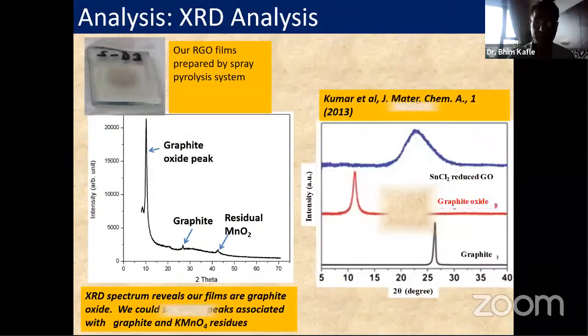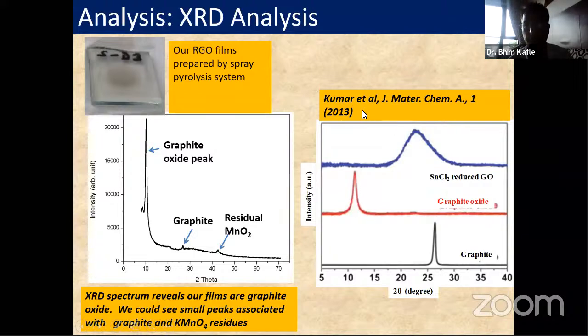And then here I would compare the XRD of the sample. This is the XRD spectra of our sample. You can see this is the graphite peak here, and this is the graphite peak published by Kumar et al. in 2013. You can see the appearance of this peak around 2 theta equal to 11 or 12, which should be compared with this peak. This intense peak of our sample hints that our sample is graphite oxide, or multi-layer graphene oxide, so several layers.